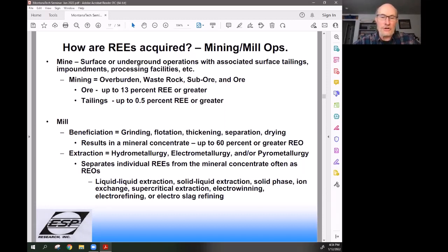We tend to do things like grinding and floating and thickening, and then doing some preliminary separations from the gangue material, and then we dry it. And you end up with a concentrate that's anywhere from 60 to 90% in rare earth oxide concentration. And then we go into the extraction process, which will come later in the separations area. And we'll talk about that a little later. Go ahead, next.